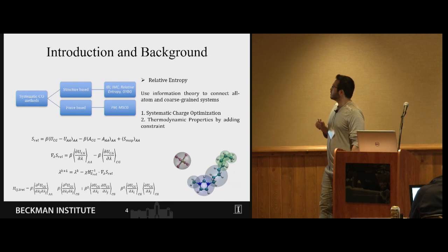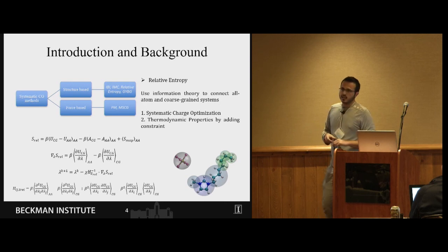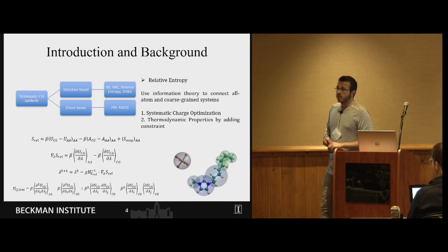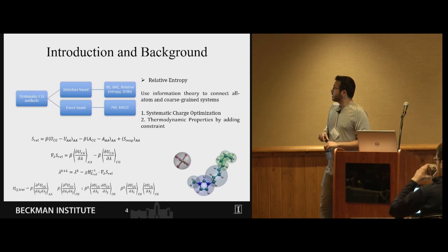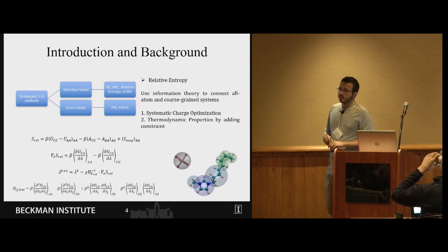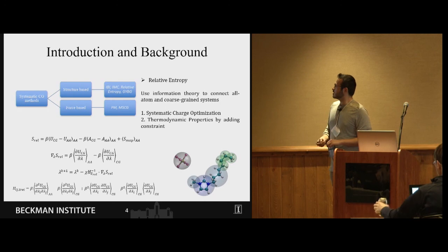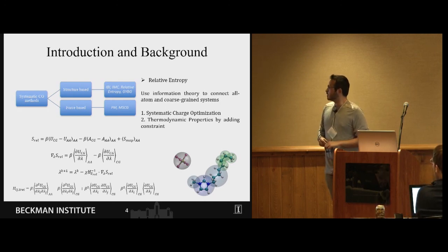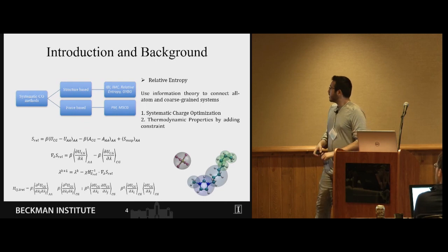We use a relative entropy method which is an information theory based method and it connects both all atom and coarse-graining systems to each other. It gives us the opportunity to optimize for charges which is not usually the case for other methods, and especially for ionic liquids charge optimization is really important because it is the most dominant interaction inside a liquid phase for ionic liquid.